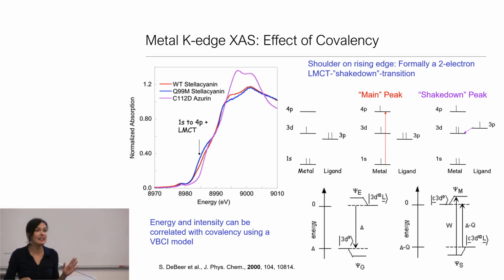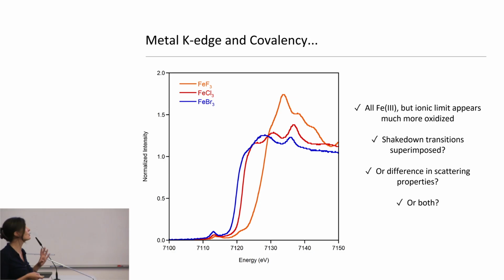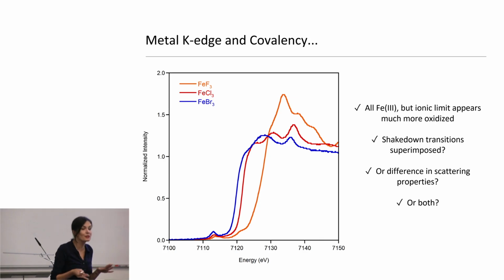In fact, the nature of the ligand is so diagnostic in X-ray absorption edges that it can shift the edges dramatically. This is an example of iron 3 with either fluoride, chloride, or bromide. And what is quite interesting is that the pre-edges are relatively similar in energy. But what varies actually dramatically is the rising edge position, where the heavier scattering bromide appears at much lower energy than the light fluorine. And this is interesting to think about, to what extent this is shakedown, to what extent this is differences in scattering property, or maybe some combination of both, right? But we know these are all iron 3. From Mossbauer, they're certainly all iron 3.